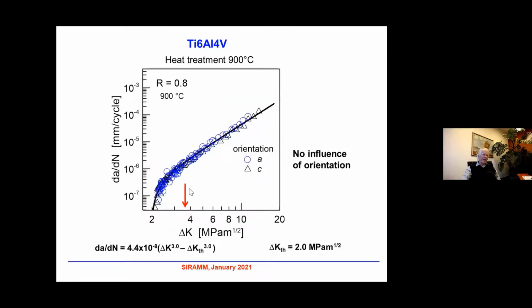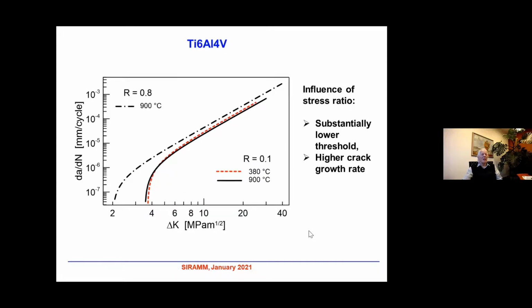And now let me say some words about the influence of asymmetry of loading. It is also important because some components are often loaded with high mean stresses and small cyclic amplitudes. This is characterized by the R ratio, which is minimum to maximum loading in a cycle, R equals 0.8. And we can see that for the titanium 6 alloy, there is no influence of orientation. Again, a nice curve can be described by this equation, and the threshold value is 2 megapascal meter to 1/2. It is a much lower value than in the case of R equals 0.1.